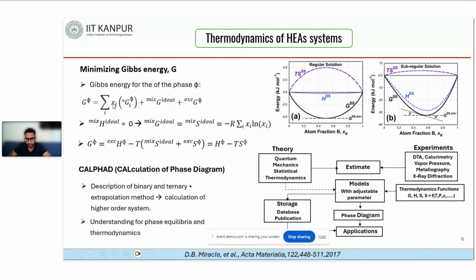we consider as 0. To predict the Gibbs energy of phases, we consider the ideal mixing of the alloy, and since the ideal mixing Gibbs energy is equal to the configuration entropy term, we have directly used this term. So at the end, the Gibbs free energy will equal the excess enthalpy minus T times delta S, the entropy due to ideal mixing, which is equal to the configuration entropy, plus the entropy due to the excess term. So to model this